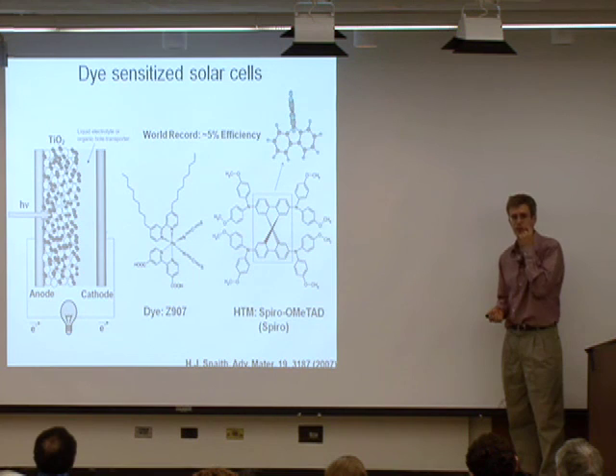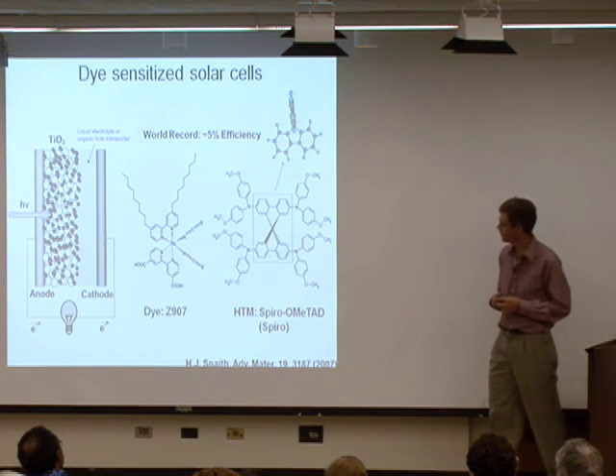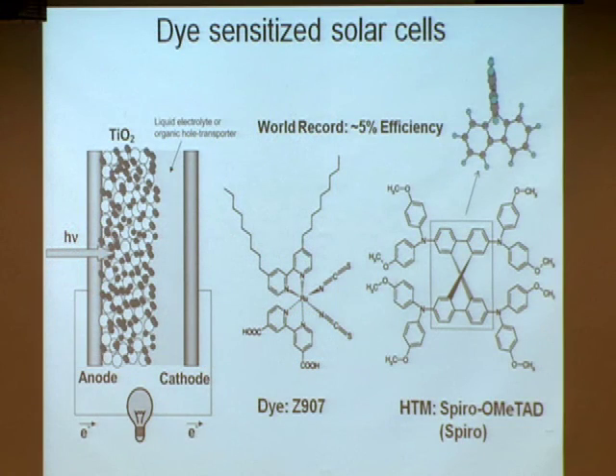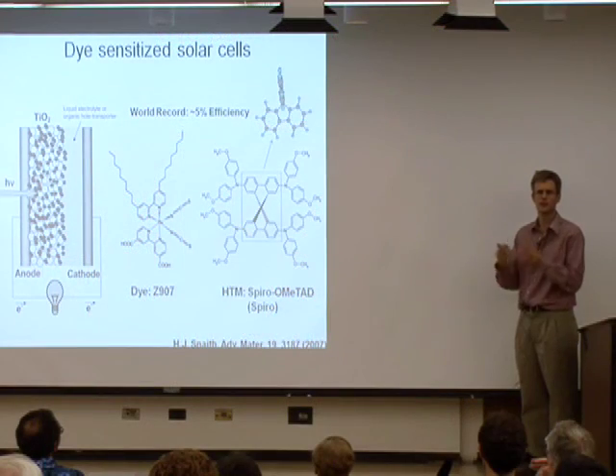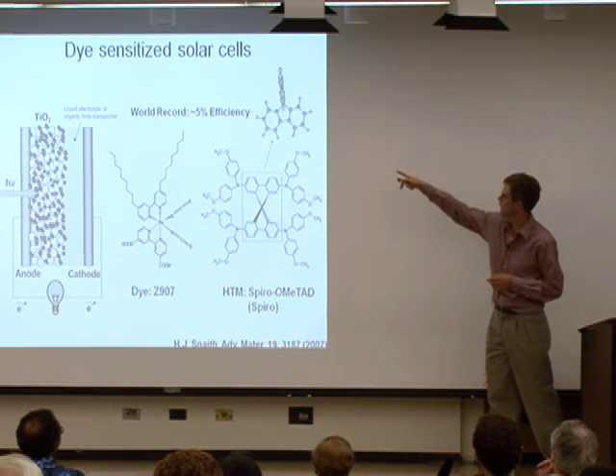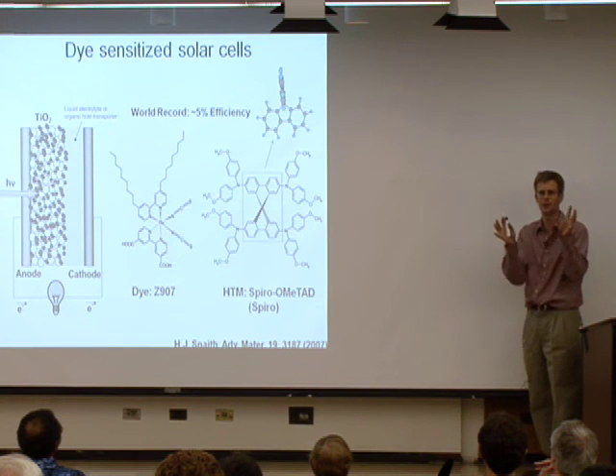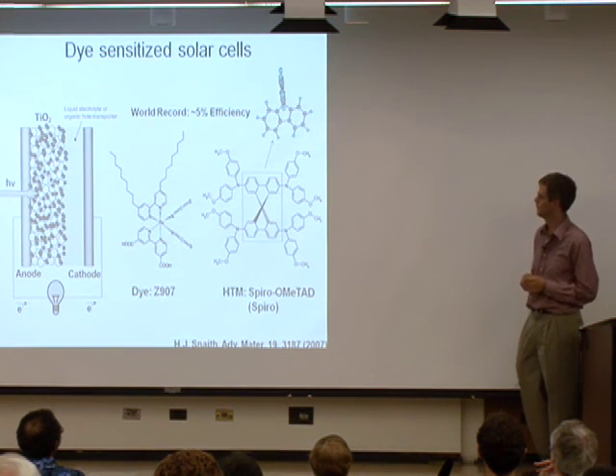Now I'll tell you about the third approach we have to making solar cells. Michael Gratzel has an approach where a paste of titanium nanocrystals is deposited on a film, and then they are covered with a dye that is able to absorb light. And after light is absorbed, an electron is transferred from this to the titania. So the TiO2 is just one of the semiconductors. And then there's a third molecule, spiro-OMeTAD, that takes the hole off of here. And so basically one molecule's job is to absorb light, the titania's job is to pull electrons out, and the spiro-OMeTAD's job is to pull the holes out of the device. So it's just a different approach, and right now the world record efficiency here is 5%. So interestingly, all three approaches are approximately tied with each other at the moment.